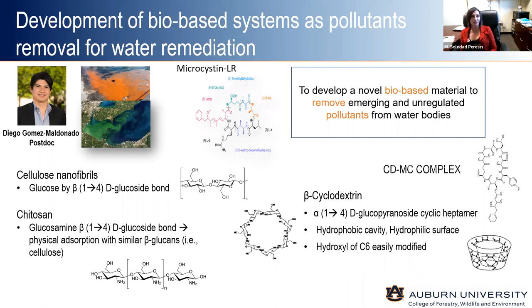We got inspired by the Great Lakes here in Michigan, with these algae blooms and the toxins generated by the algae, which are very toxic and bad for human and wildlife health. We particularly focus on this microcystin LR and try to develop these cellulose-based materials. We also play around with other types of polysaccharides. In this case, we created these complexes using beta-cyclodextrin and created several different assemblies of this material, moving towards creating this capture capsule, taking advantage of the hydrophobic cavity of the cyclodextrin and the great absorption capability of cellulose and chitosan, to create materials that will capture the microcystin LR into the systems.